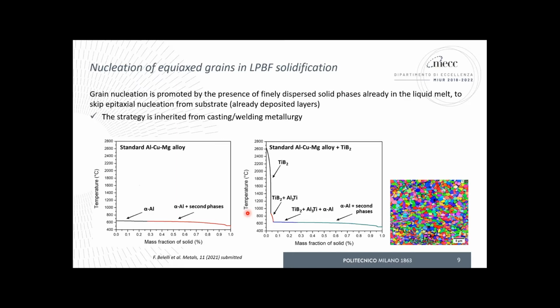We can promote the nucleation of equiaxed grains by creating a dispersion of solid phases that already exist in the liquid, not any kind of phases. Maria Teresa was explaining that we need to have some special properties, but more in general, we have some standard particles that have been used for lots of years, also in casting and welding metallurgy, to promote nucleation of new grains in the liquid melt. Titanium diboride is a typical one. It's a typical compound that can be used, and you can see the big difference that we can create in the solidification curve by adding TiB2.